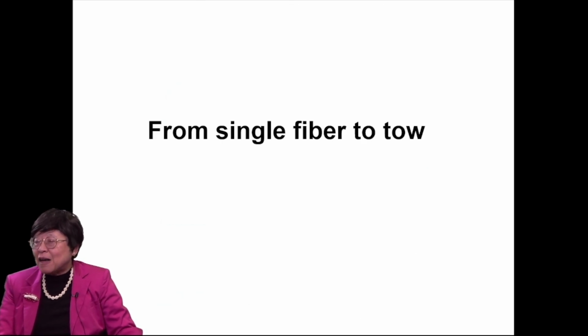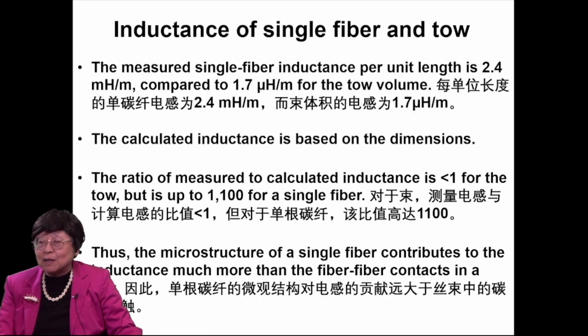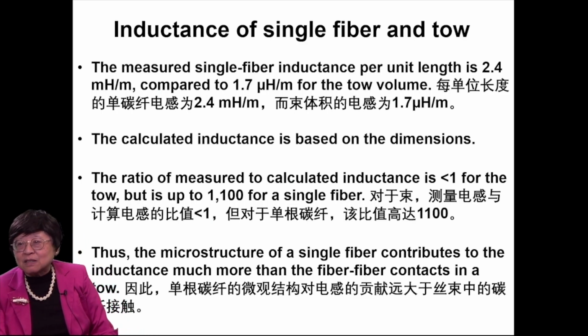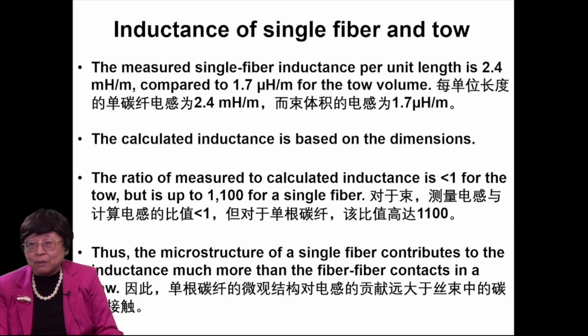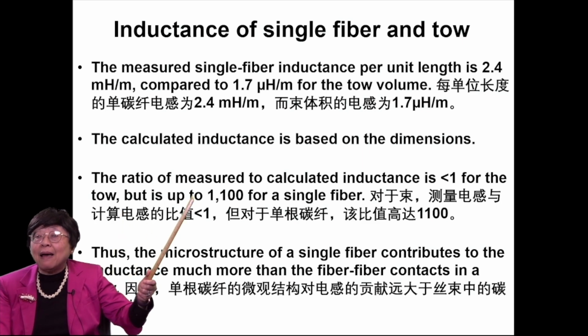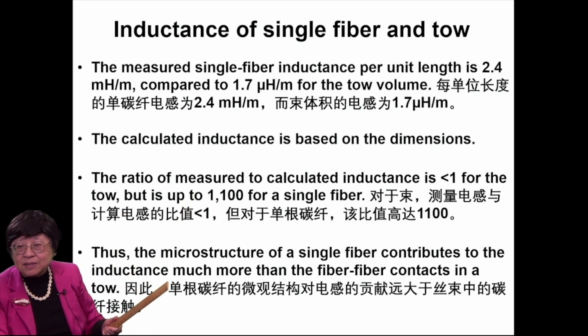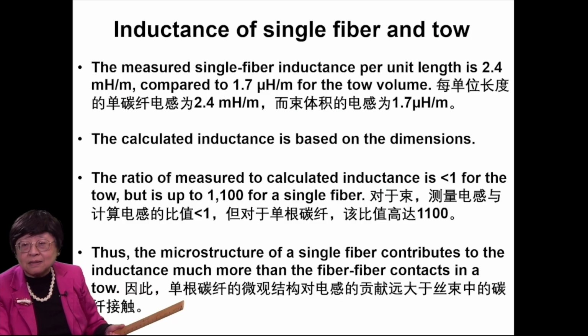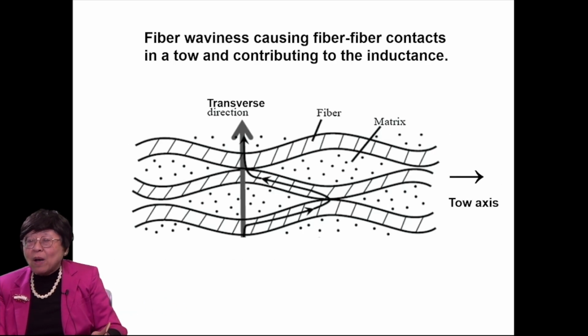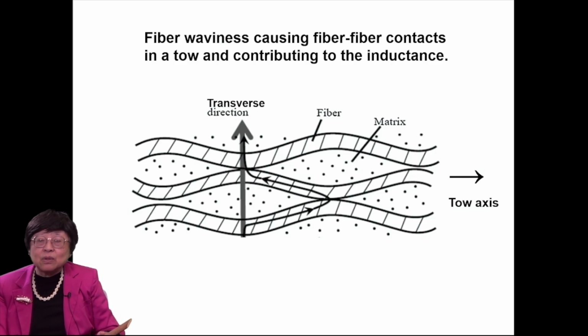Now let's move from single fiber to tow. Okay, 12,000 fibers in a tow. The measured single fiber inductance per unit length is 2.4 millihenry per meter, compared to only 1.7 microhenry per meter for the tow volume. Again, the calculated inductance is based on the dimensions. And the ratio of the measured to calculated inductance is less than 1 for the tow, but it's up to 1100 for a single fiber. Thus, the microstructure of a single fiber contributes to the inductance much more than the fiber-fiber contacts in a tow. The fiber waviness causes fiber-fiber contacts in a tow, and thus contribute to the inductance.